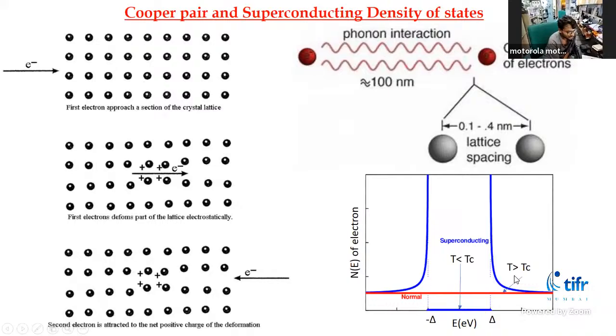Above Tc, all materials behave like a normal metal or semimetal, whatever it can be. Here with the red line, that is the normal state, I am showing you the density of states in terms of energy. It should be flat, like I'm showing in the red line. But when it becomes a superconductor, when Cooper pairs are formed, from minus delta to plus delta, all are Cooper pairs. There are no electronic states available. So in the superconducting density of states below the critical temperature, there are no electrons in this gap, only condensed Cooper pairs.